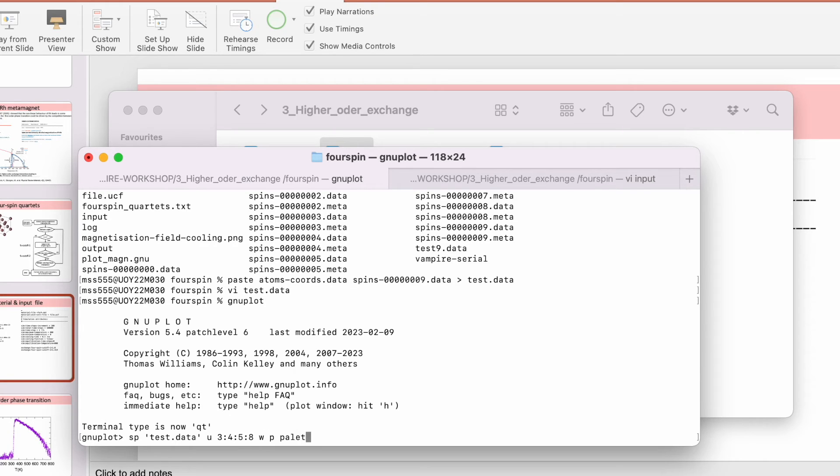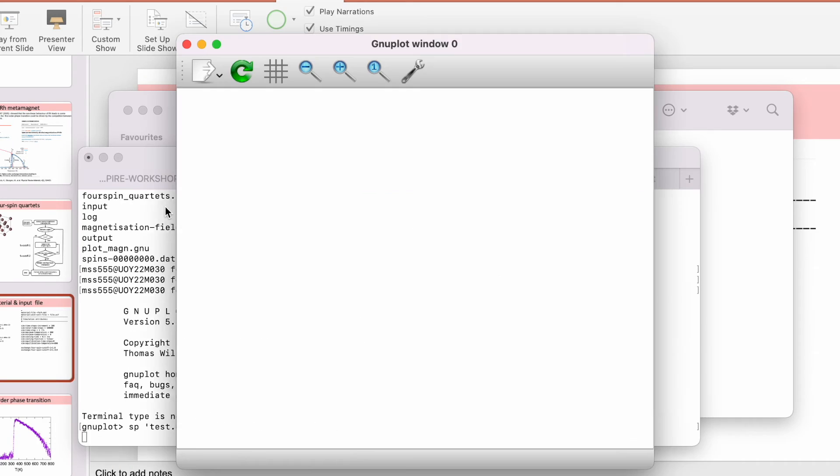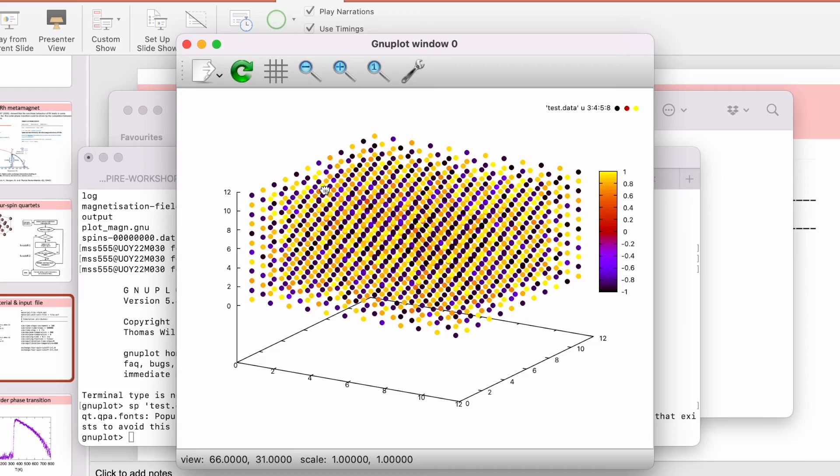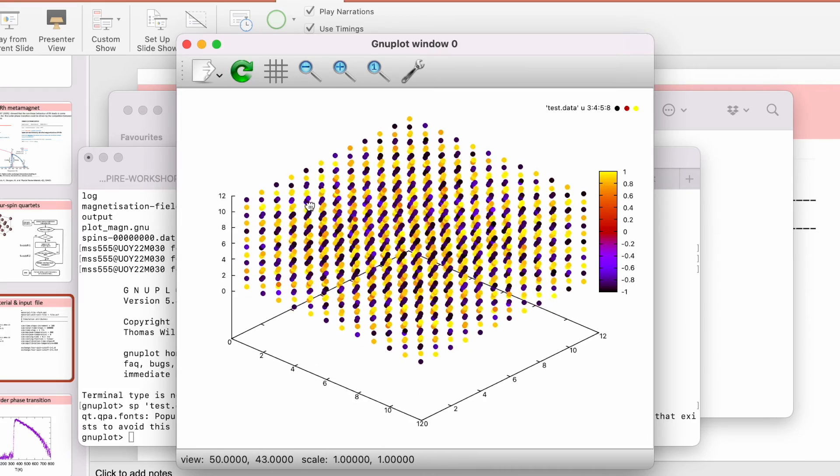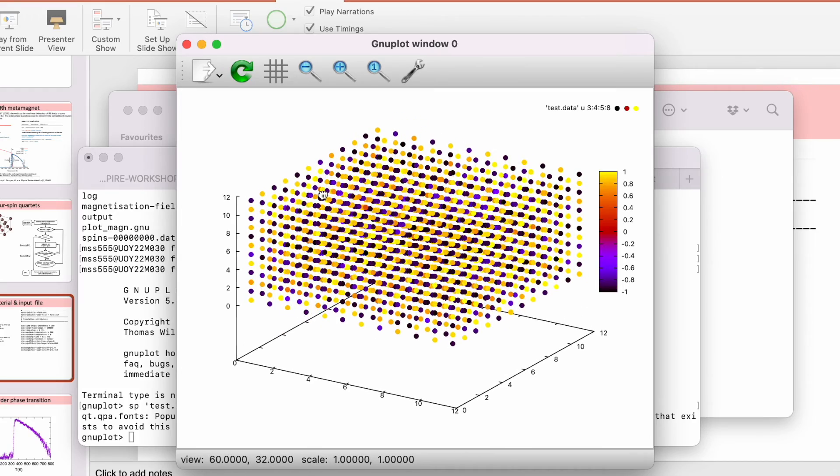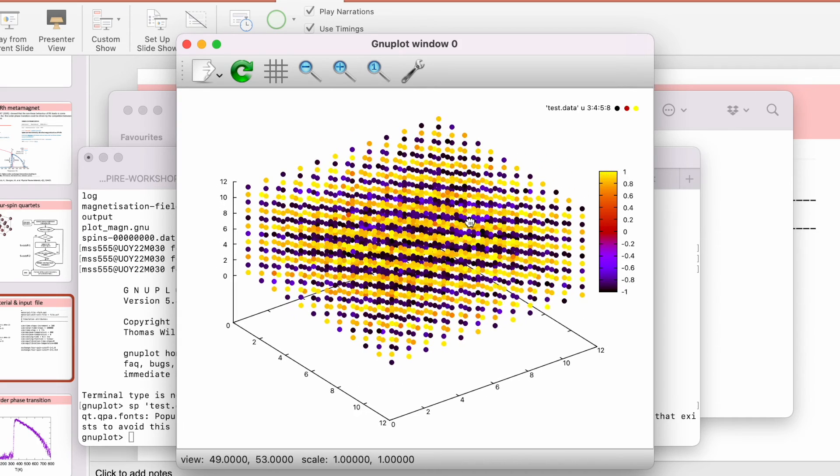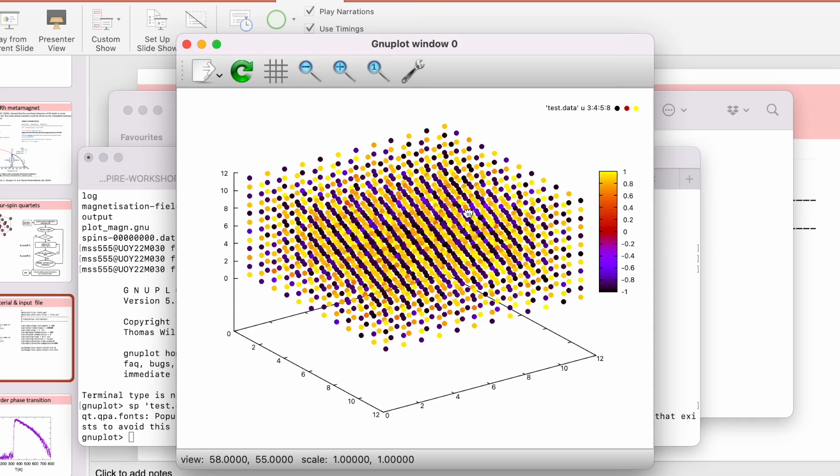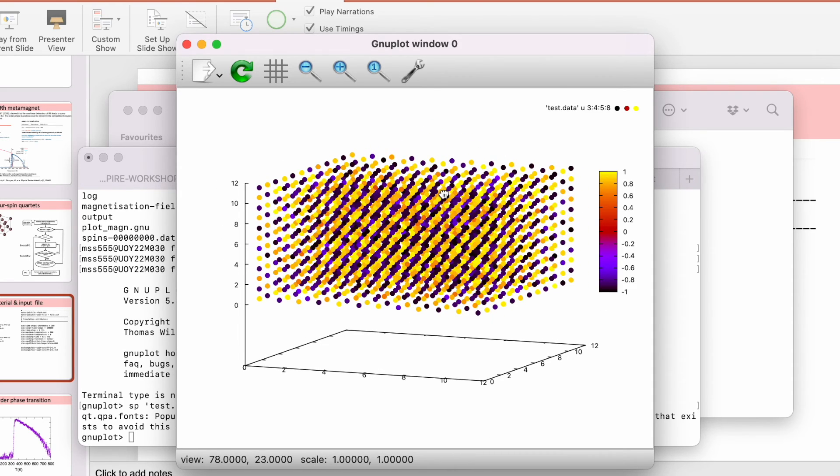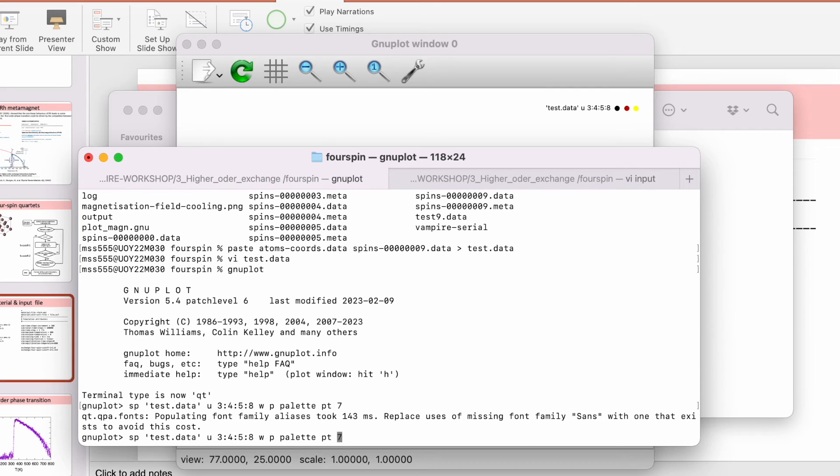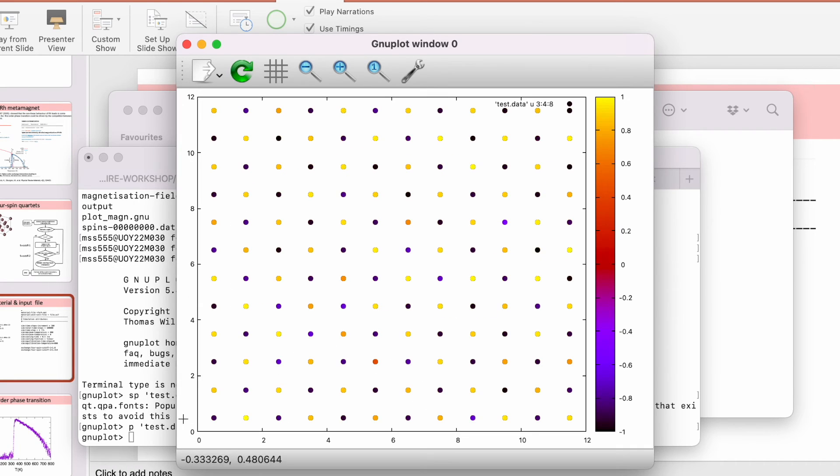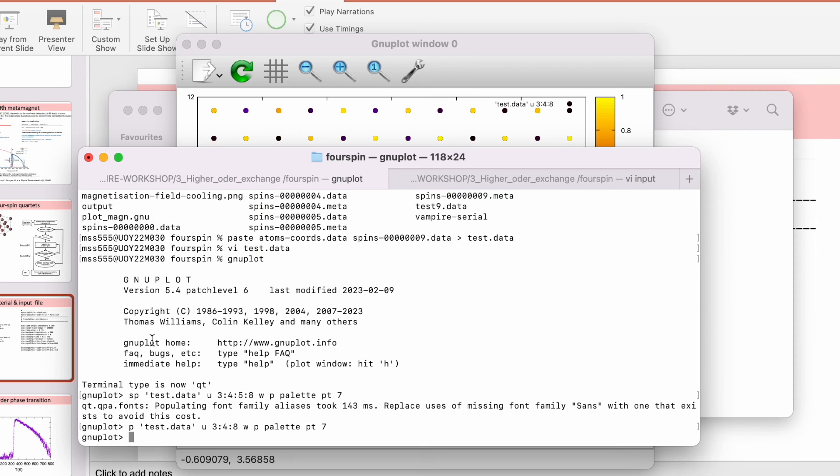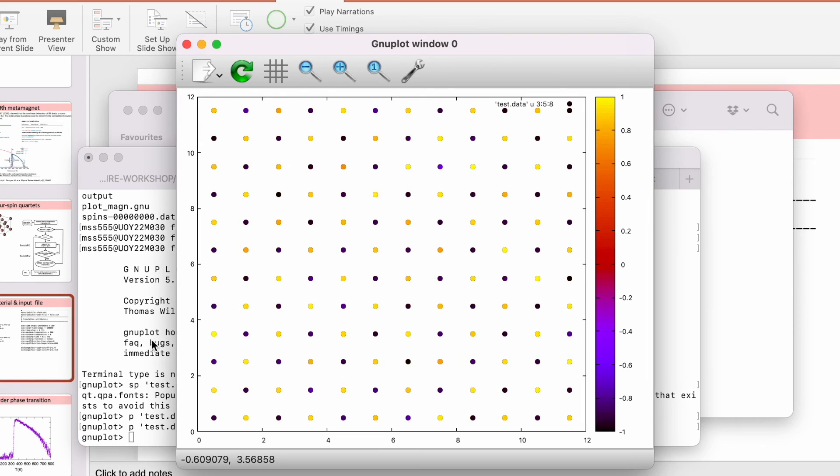Three, four, five represents the XYZ position, then column eight is the Sz, the spin value on Z. This is the last spin file, so this is the low temperature regime. We see actually the antiferromagnetic forming here, with yellow being the spin up and black being the spin down atoms. Maybe it's easier to look at this in 2D. I'll just plot this as X, Y, and then again the spin. We have this checkerboard spin orientation corresponding to an antiferromagnet.